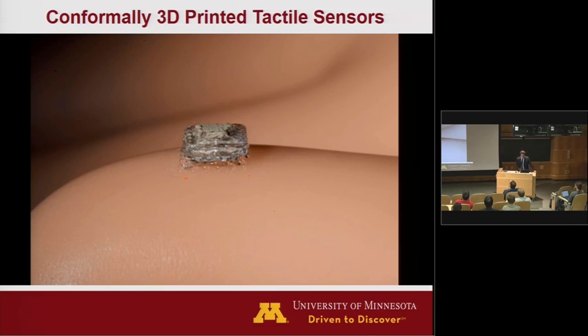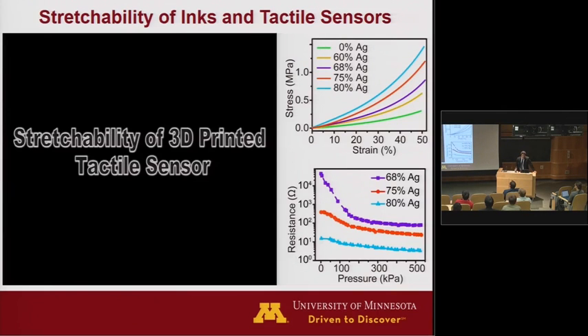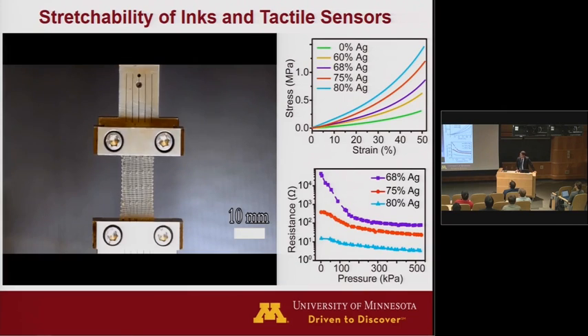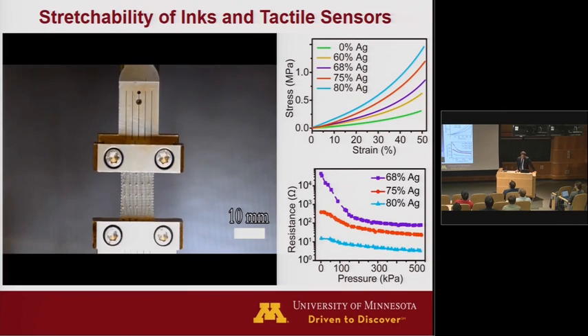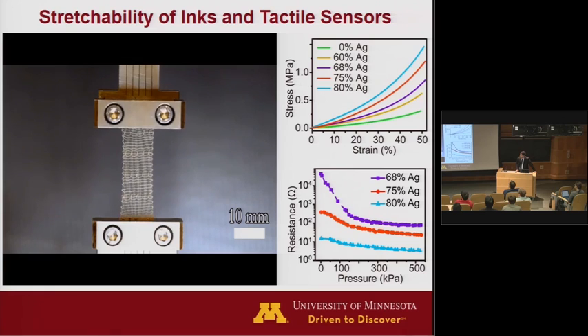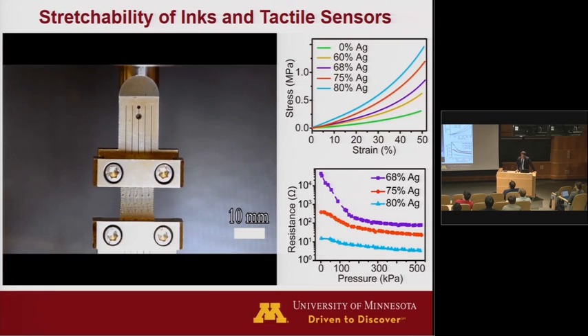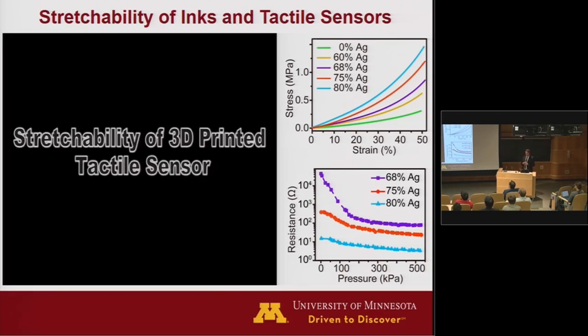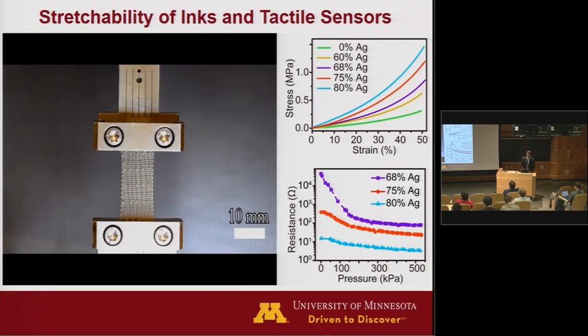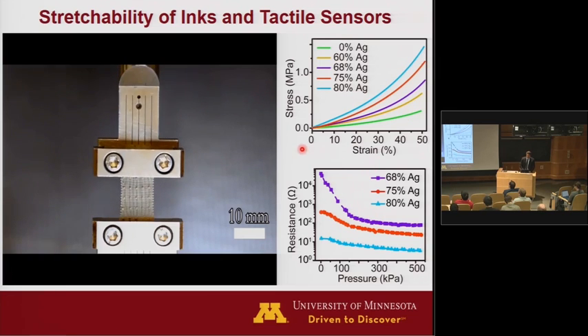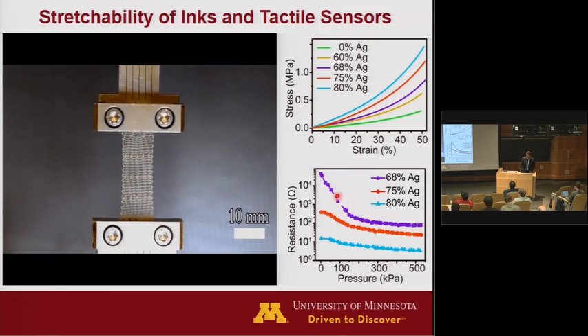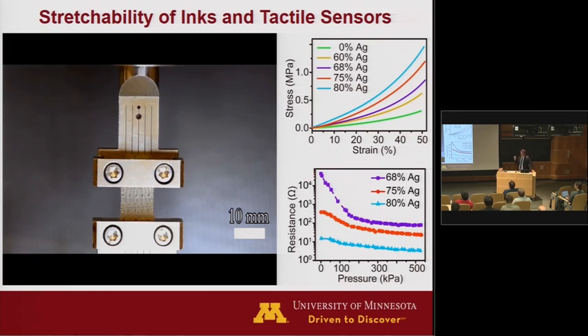So it's getting kind of fancy at this point. Now these are conducting inks that are basically fabrics. So this is a silver particle within an elastomeric matrix. You can see it can be stretched up to 3 times. So a stretchable fabric, where the mechanical properties of this fabric depend on the silver content loading within the elastomeric matrix. But the key thing here is that you can pick a silver composition for that middle coil, which is exactly at the percolation limit of the particles within the elastomeric matrix. So that gives you the most sensitivity to touch and to tactile sensation. If you pick this 68% loading here, you can see they have the largest change in resistance.